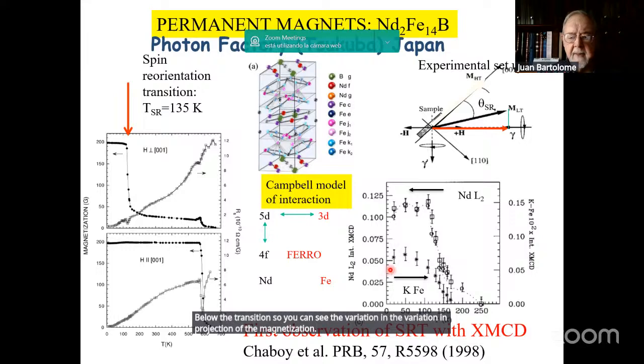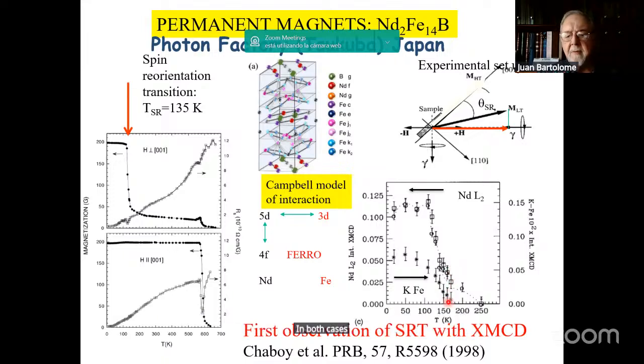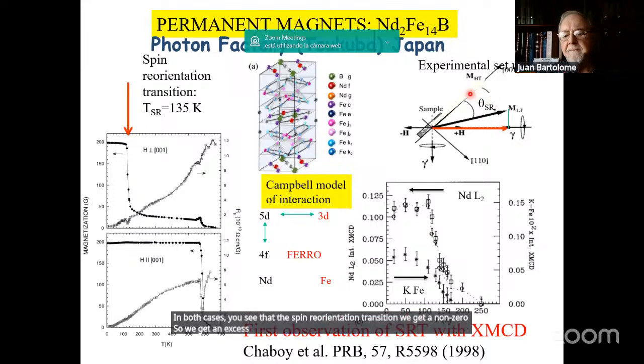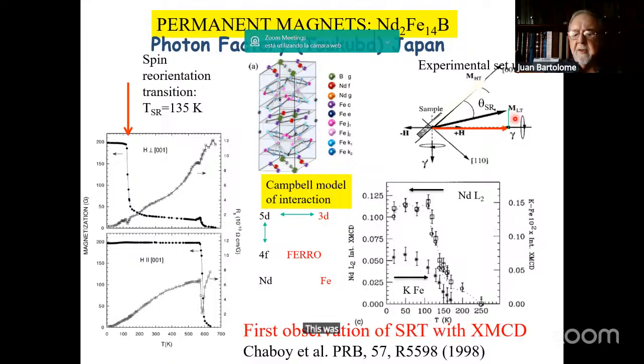This you can see here in the experimental results as measured on the neodymium L2 edge and on the iron K edge. In both cases, you see that at the spin reorientation transition, we get a non-zero, so we get an excess in signal, which is the difference between the two projections. This was actually the first observation of a spin reorientation transition with XMCD.